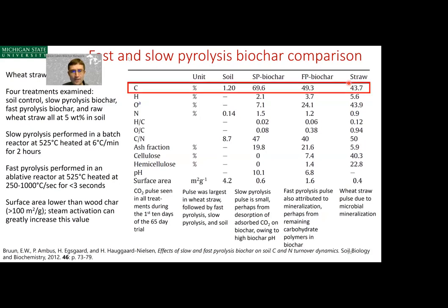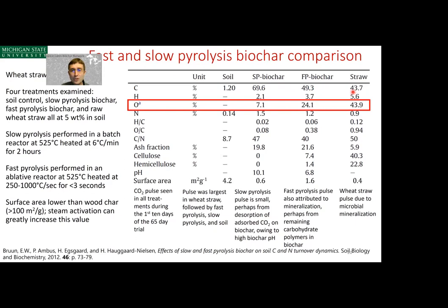Looking at the carbon content, you can see the slow pyrolysis biochar has about a 70% carbon content, whereas the fast pyrolysis biochar is at 49%, only slightly higher than the untreated straw. The oxygen contents are also very different. The slow pyrolysis oxygen content is about 7%, and the fast pyrolysis oxygen content is 24%, both substantially lower than the 44% oxygen content of the original wheat straw.